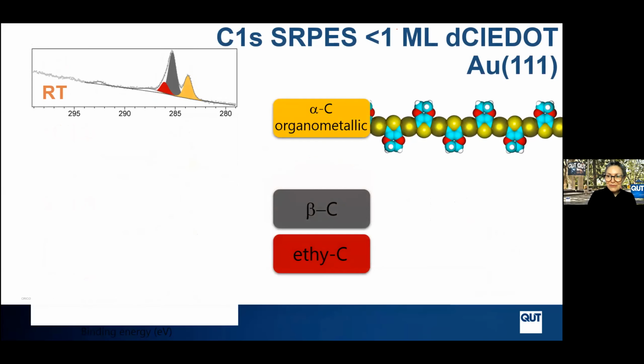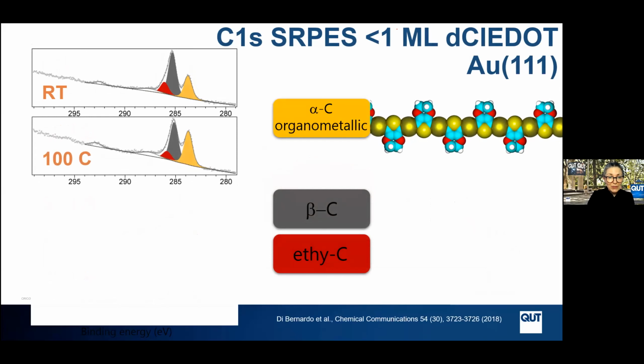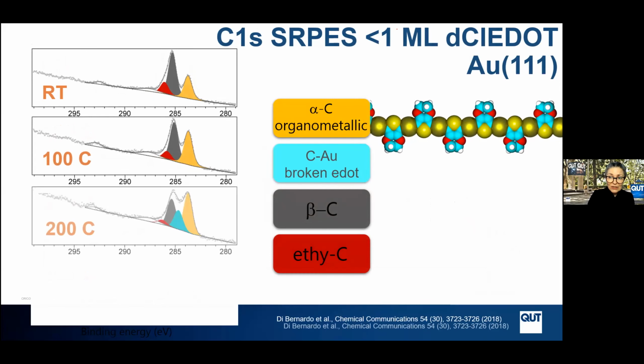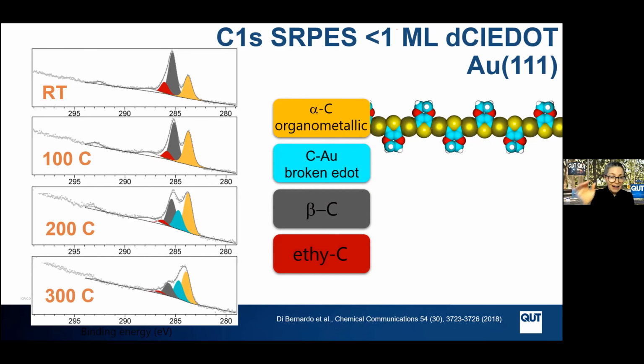On gold, we find a different problem. The rising background shows you how difficult it was to stick the molecule to the substrate. We get an organometallic at room temperature. Things continue to look okay with moderate heating, but the molecule breaks. And heating it more does not convert the organometallic to a covalent polymer, but instead leads to a broken molecule.